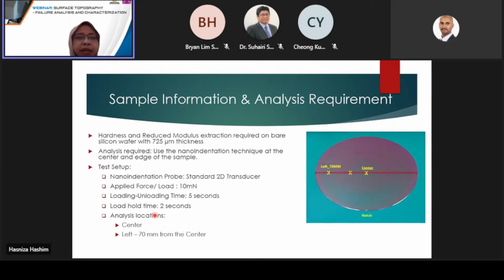Okay, the objective of this testing is to extract the hardness and modulus from the silicon wafer. So the analysis requires indentation at the center and the edge of the samples. We are using the 2D transducer probe. We apply a force of 10 millinewton with a loading and unloading segment time of 5 seconds and a hold time of 2 seconds.